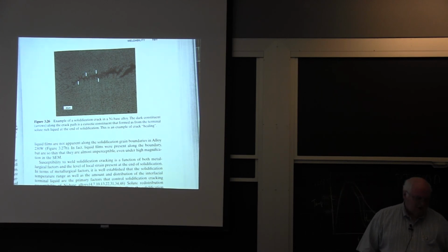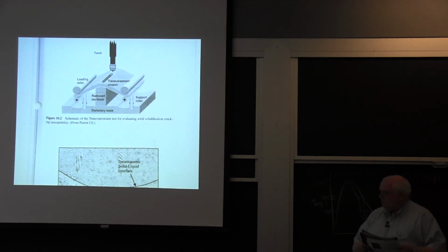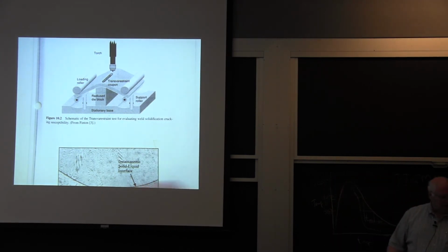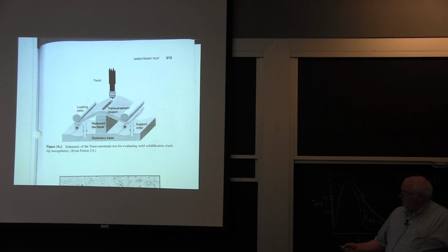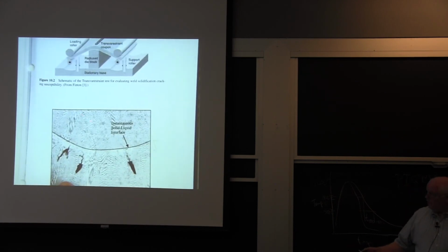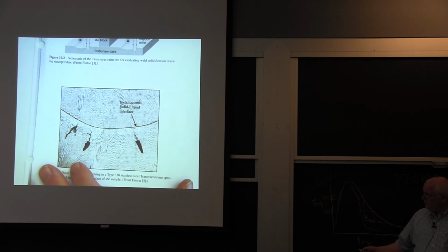But you know, if you go look at the literature, they'll talk about solidification cracking of steels. I don't know if I should say I've never seen a solidification crack in steel, but I haven't seen very many. Okay, and I talked about this the other day when we were talking about stainless steels. This is the Rensselaer Polytechnic Varestraint test, where you basically weld on a stainless steel or a nickel-based alloy, some high alloy typically. You make the weld, and as you're welding, you just bend the plate along the weld. It's called a trans-Varestraint test, and you can see when you applied the pressure, and you just open up the cracks. Okay, because the cracks were partially liquid at the time, and you open it up, make more space.